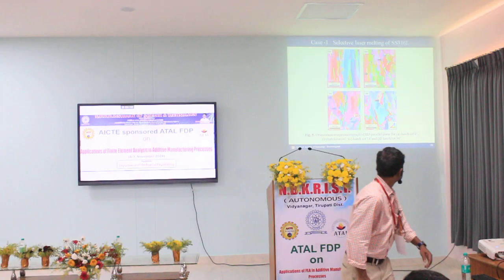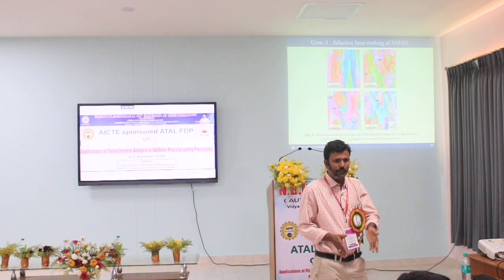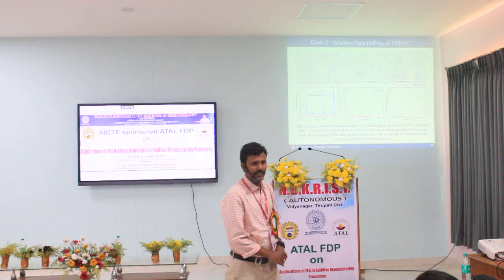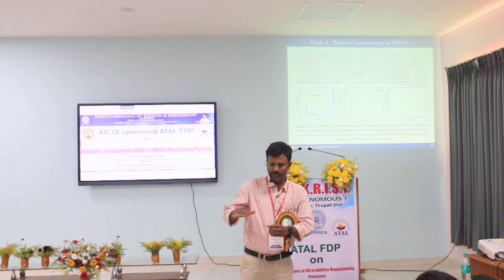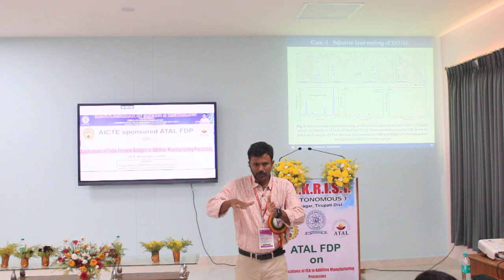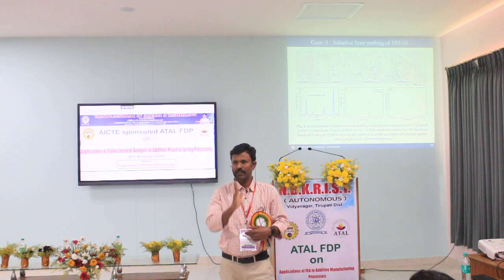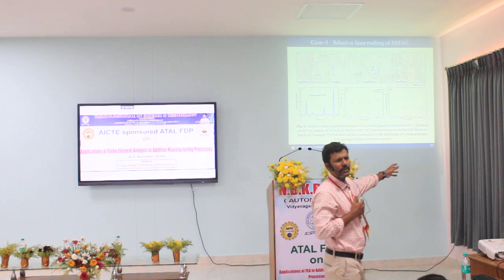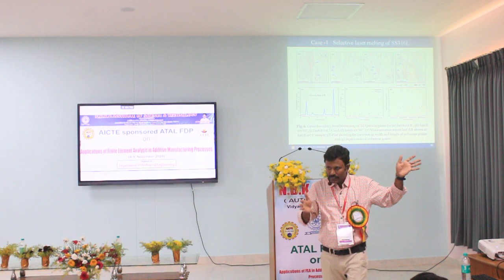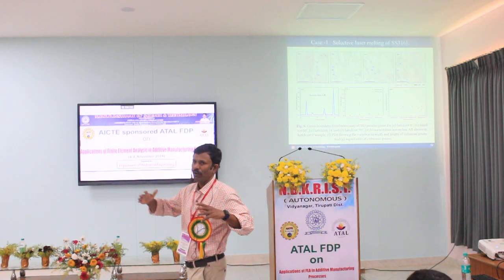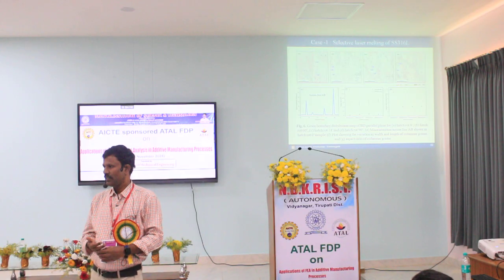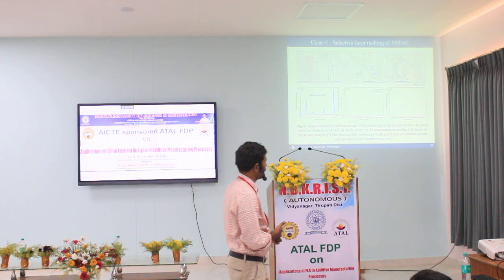Yeah, this is the melted vertical column, the deposition column grain orientation we have made, and the related grain boundary distribution. First one, if I build like this, on the top surface. Second, on the wall side, the build direction, the center direction. Huge variation, significant variation. This is the reason for the wide variation of mechanical properties in different directions in additive manufacturing: build direction and normal to build direction.